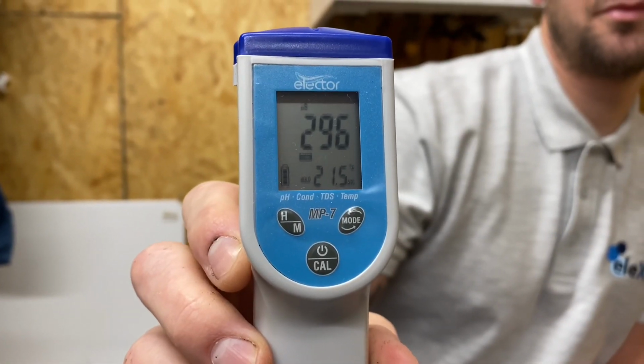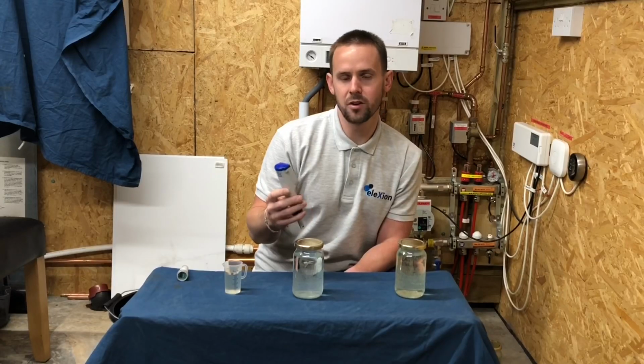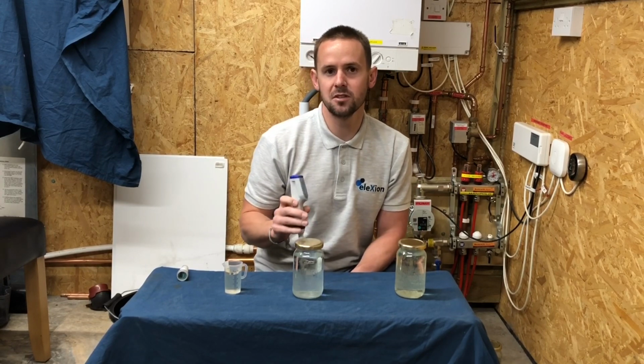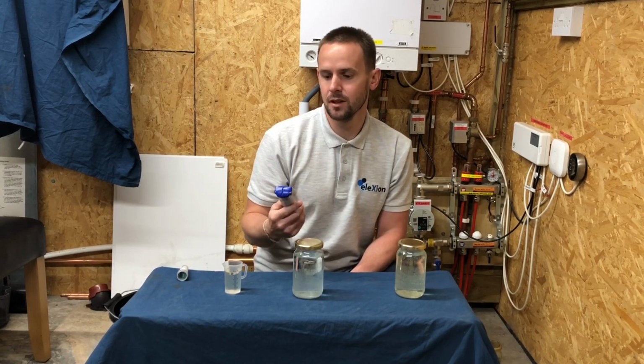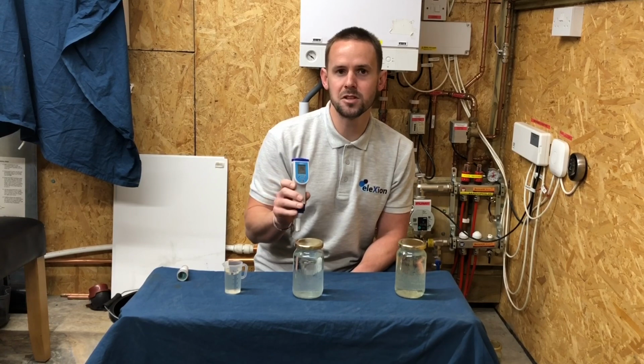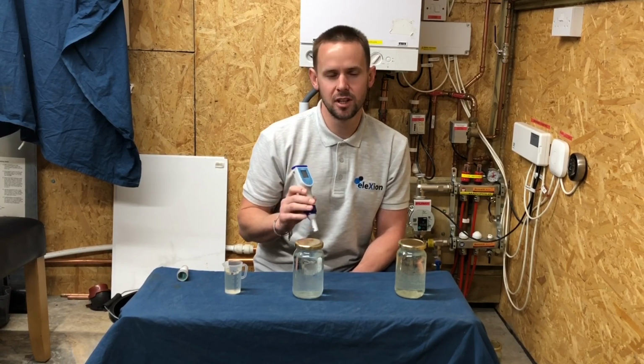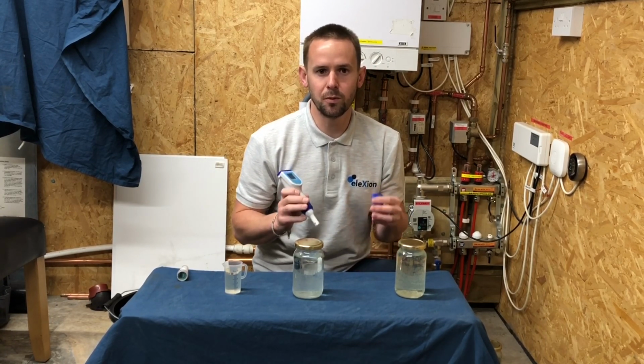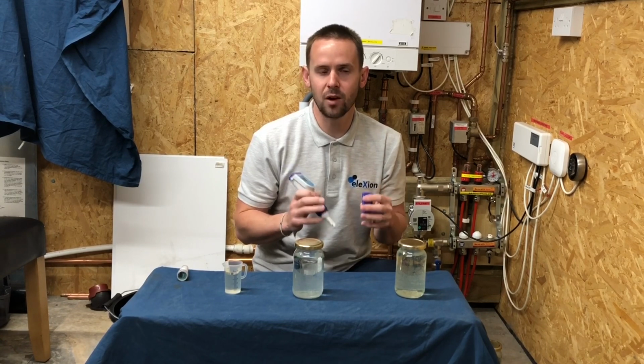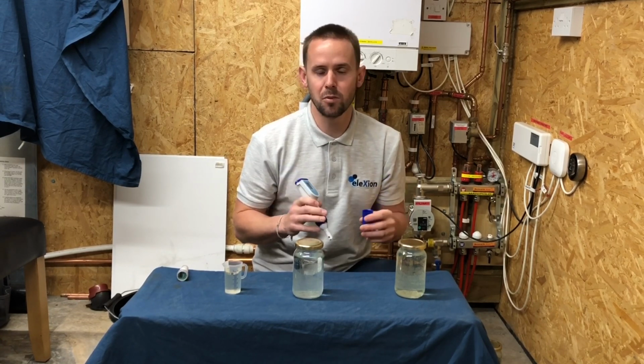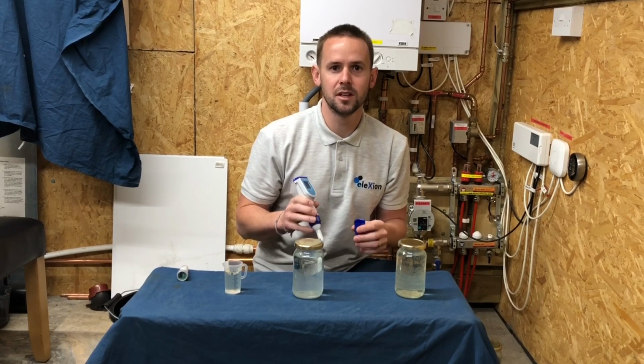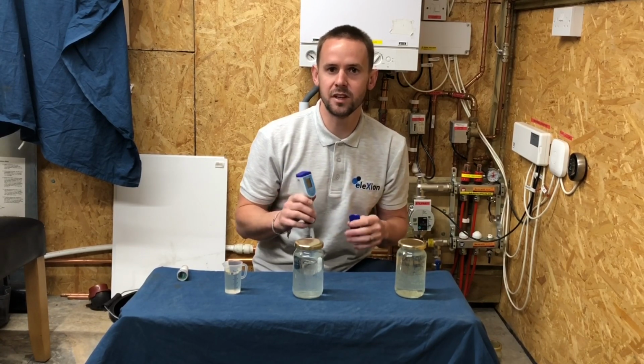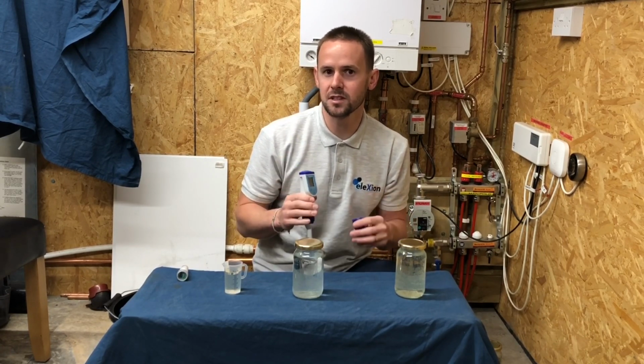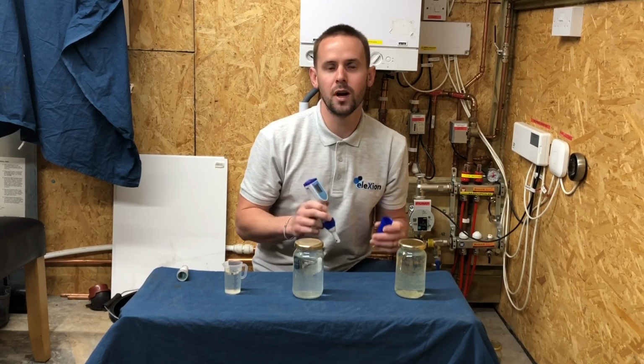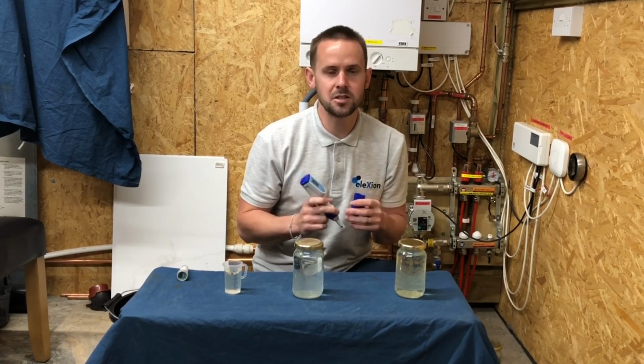So it's come out at 296 microsiemens. That's rather interesting because the tap water we tested originally was 198. So it's increased by 100 by having a bit of residue there from the cleaning agent. It's really important, when we're doing our testing, to make sure we get all the system flushed properly and remove any chemical we might have put in, because otherwise it will increase the conductivity, and what we want is a low conductivity. So it's really important to test before, test afterwards, and test during your flushing.